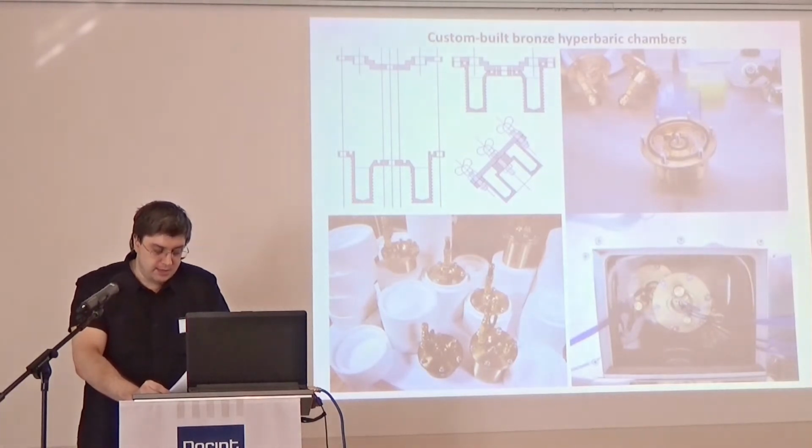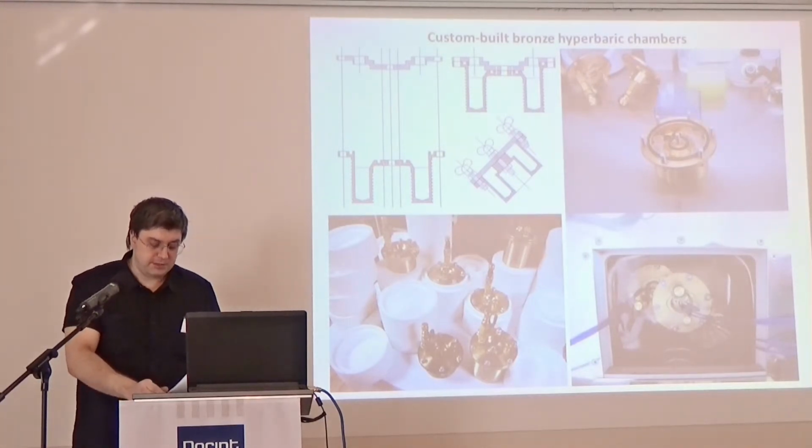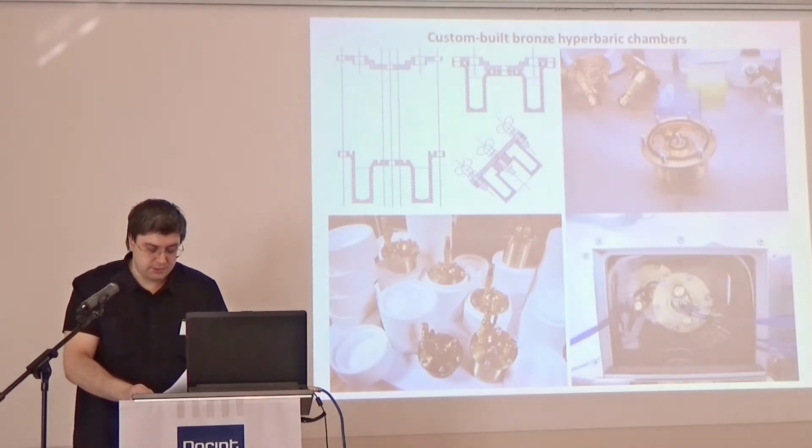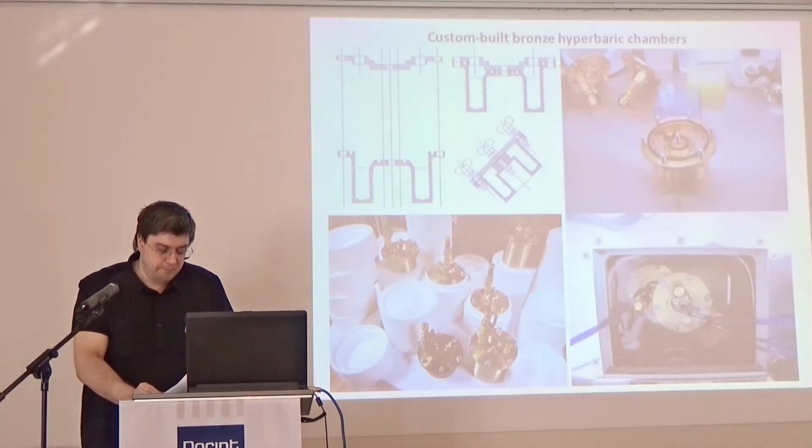Even after designing a sophisticated decompression protocol, we could not achieve survival upon thawing, as opposed to a joint application of xenon plus 5% dimethyl sulfoxide that usually showed more than 80% of survival. This made us disappointedly conclude that xenon has no cryoprotective properties applying slow programmable freezing.